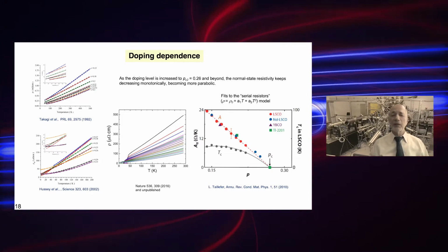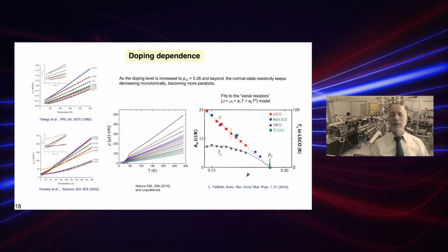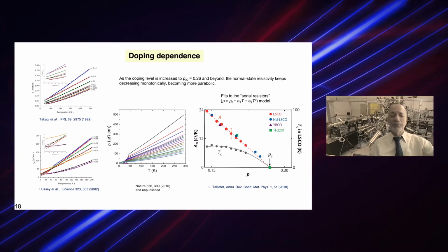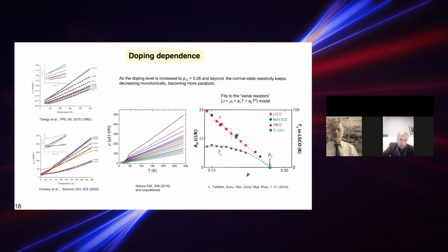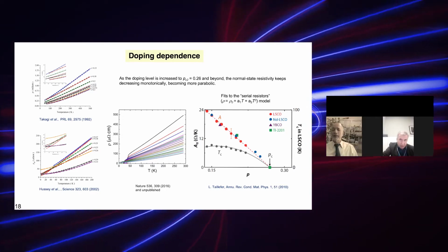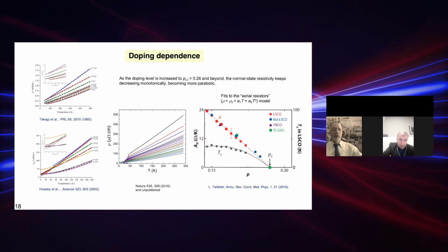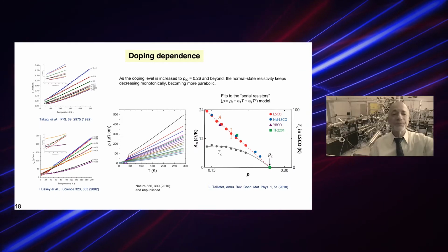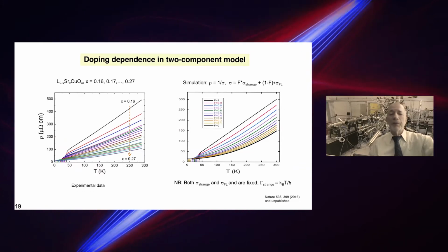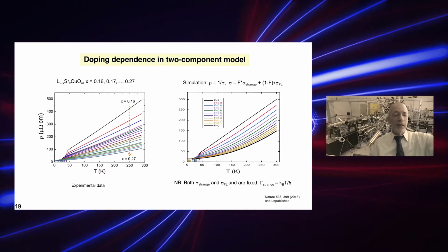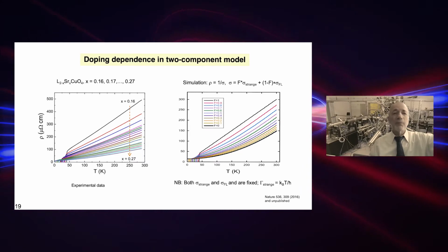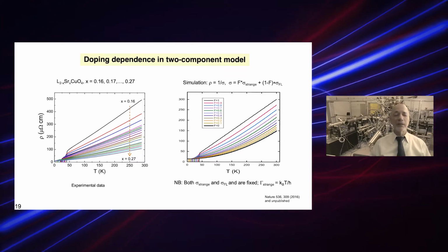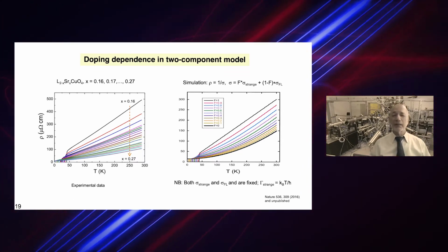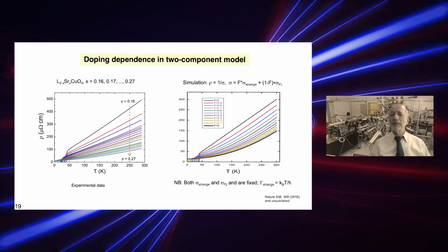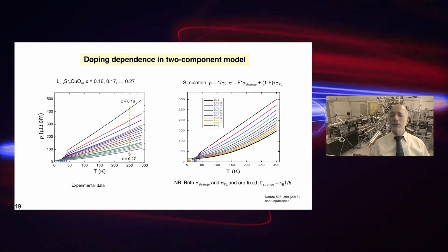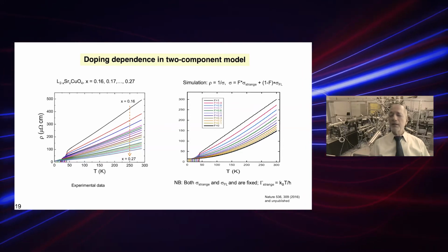That can actually be seen visually without any fitting from the figure in the middle. You see that the top one is pretty much a perfectly straight line, and then the bottom one starts looking more parabolic. Now, I can also try to fit this by a two-component model. These are the same experimental data to the left, and to the right is simulation.